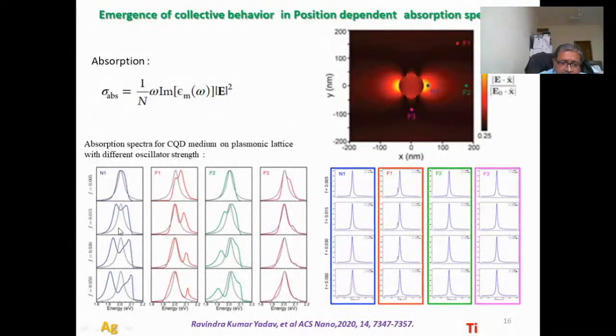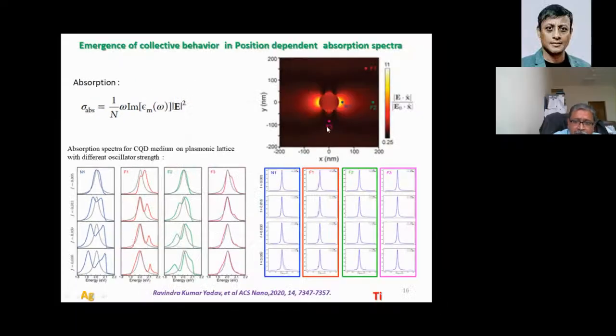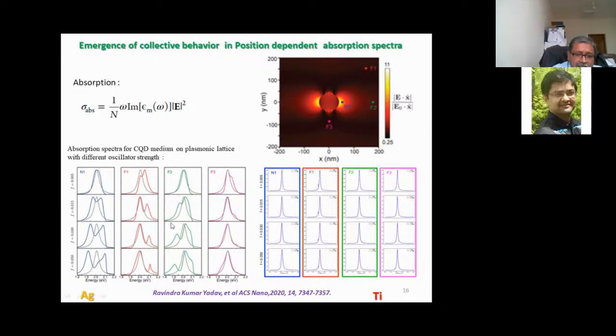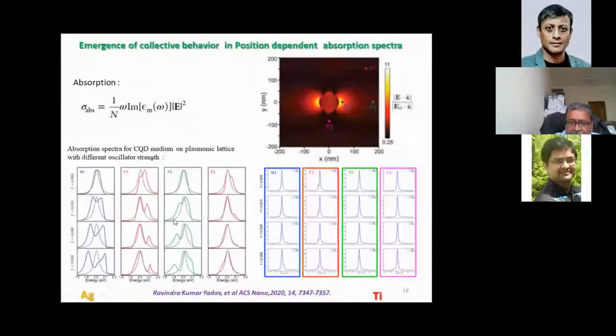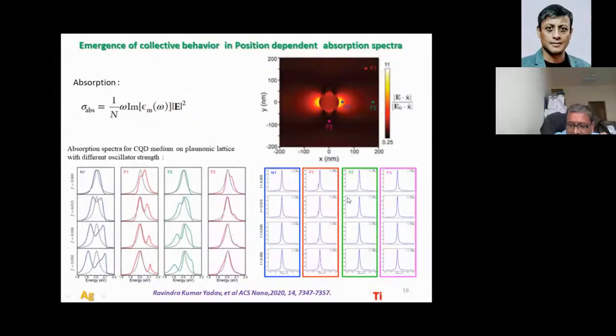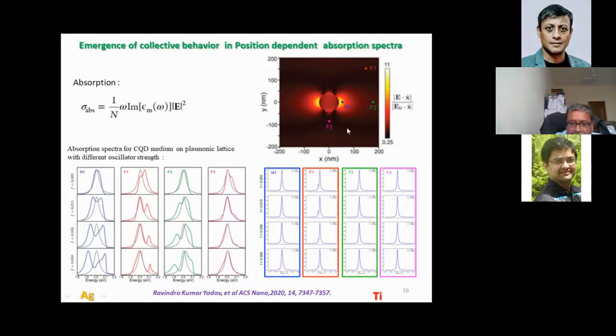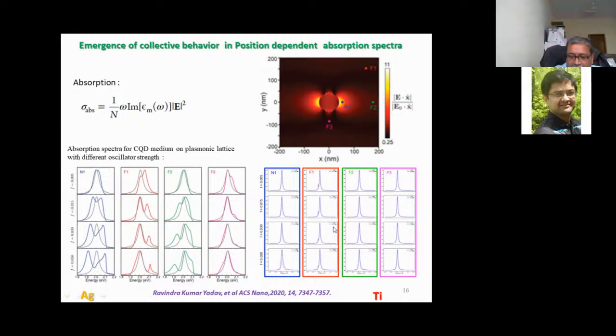So you can see that the absorption spectra is quite strongly dependent on the position, right? And that's indicative of the fact that it is not necessarily only a local effect, but also a non-local effect, and it involves the presence of SLR. It means it needs both LSPR and SLR. You are not able to decouple the effects individually, but it's very clear you need both. More so when the simulations were run with something else, titanium, with the same lattice, everything the same, and you look at the same position, you don't see this splitting at all, right? Except for this one position here, which has no LSPR, but has a weak lattice mode.